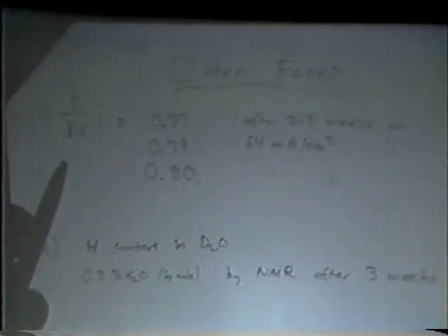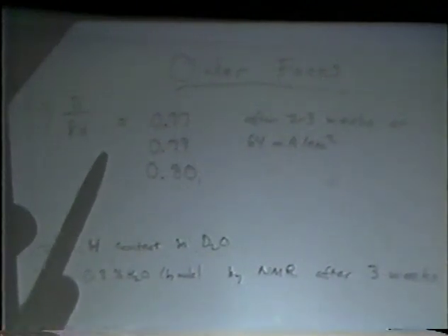You simply pull out your palladium rod and then deposit it into a tube. The tube contains argon so that when you evolve the hydrogen, you don't recombine it with oxygen and explode yourself. And you displace water. And you can displace 100 cubic centimeters of water out of one of these reasonably small diameter rods and measure that very accurately, and then analyze the gases and make sure that they're deuterium. You can take a Bunsen burner to accelerate the process, or a propane torch, just heat up the palladium, it all comes out in 15 minutes, and you have a very easy method of analyzing the stoichiometry.